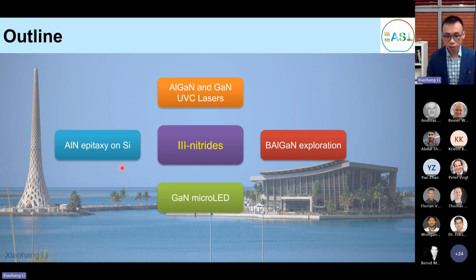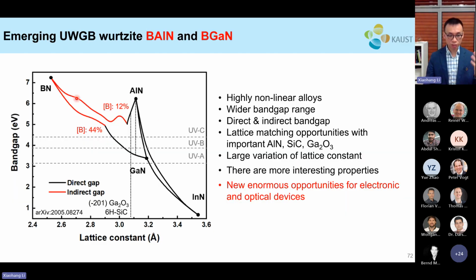So after discussion of the gallium nitride micro LED, I would like to talk about the exploration of the boron aluminum gallium nitride system. So I showed this graph a little bit earlier. If you look at boron aluminum nitride and boron gallium nitride, you will find that these are highly nonlinear alloys, not only when looking at the band gap versus the lattice constant. But it has some distinct characteristics. Number one, it can offer a wider bandgap range to about 7.2 eV.